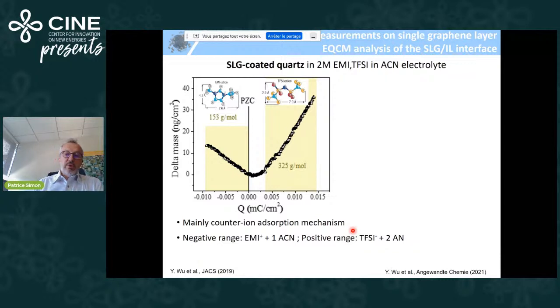Then we did some gravimetric experiments, and you can see here the change of the weight versus the charge. And what you see, a striking difference here, is that you have on positive charge a very linear slope, which corresponds to anion adsorption, and on the negative side a linear slope, which corresponds to cation adsorption. And we have more or less cations and anions adsorbed with 1 and 2 acetonitrile molecules.